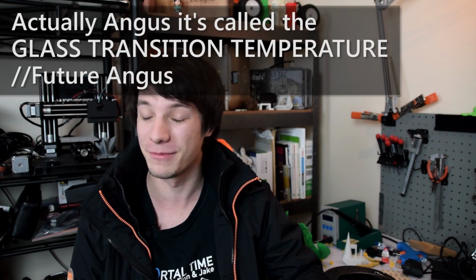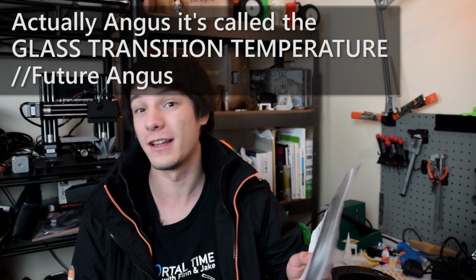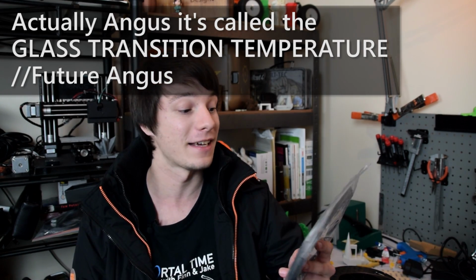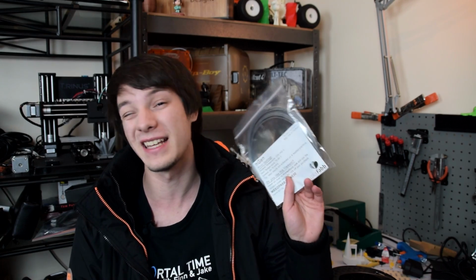So recommended settings of 220 to 240 degrees C, bed temperature of 75 to 85 degrees C. Now this surprised me, as most PETs, they recommend a lower bed temperature because of the quite low glass transition temperature, where it will start softening at quite a low temperature compared to, for example, ABS. Now, this is quite a high bed temp, and I'll go into a few issues I had printing with NGen, but essentially it's saying best results are achieved with a heated platform. I would say you probably are going to struggle printing this without a heated platform.